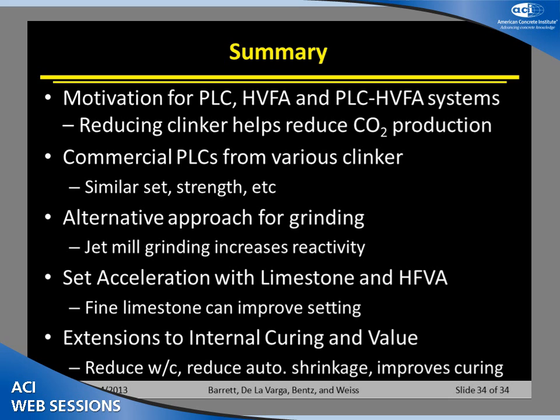Set acceleration with limestone, so we can offset some of the slow strength development in high volume fly ash mixes with fine limestones. And then we can use internal curing as a way to help offset some of the slow strength development by changing our water to cement ratio, but then we can account for the reduced autogenous shrinkage, we can improve the curing, and we can reduce things like chloride ingress in those systems.